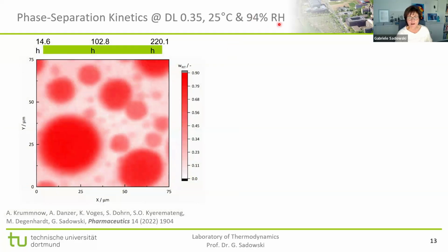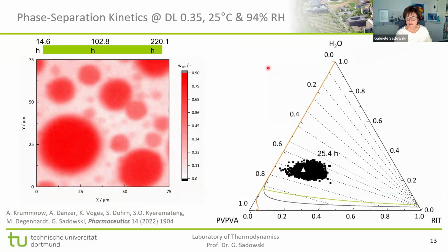And this is now at very high relative humidities. This is not the relative humidity that's relevant for storage, but we have chosen this because we would like to mimic the RH or surrounding of the tablet during a dissolution process. And this is the phase diagram. So this is what we use now to explain this behavior.